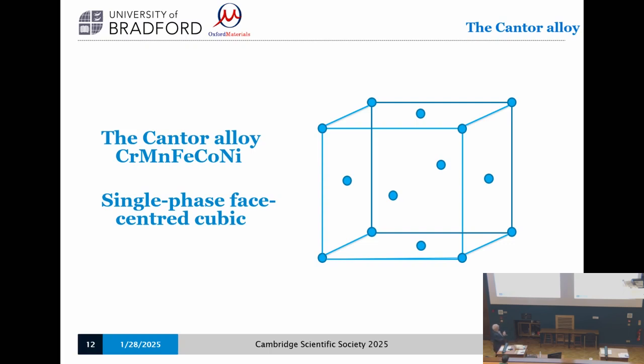Only one of these 5 components is actually face-centered cubic at room temperature, nickel. And if you mix them in binary or ternary systems, they don't always form it, even if you set the composition right. It's only when you're in the middle of the phase diagram, in the middle of the composition range, that they form this single structure. So this was a completely novel observation.